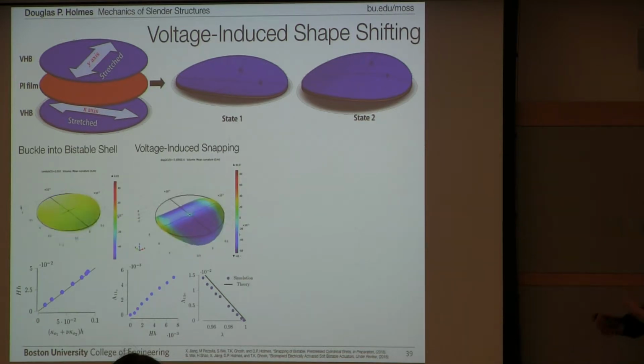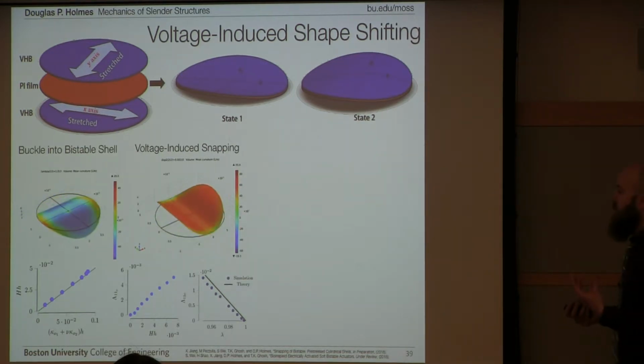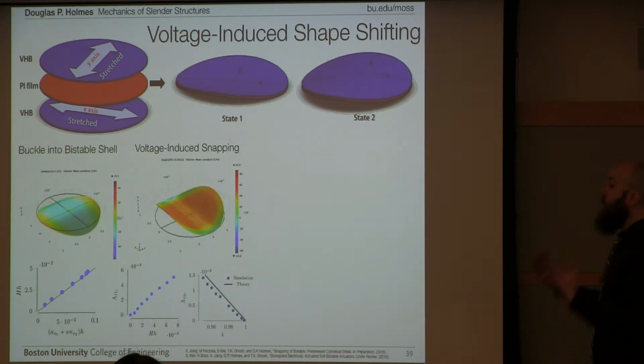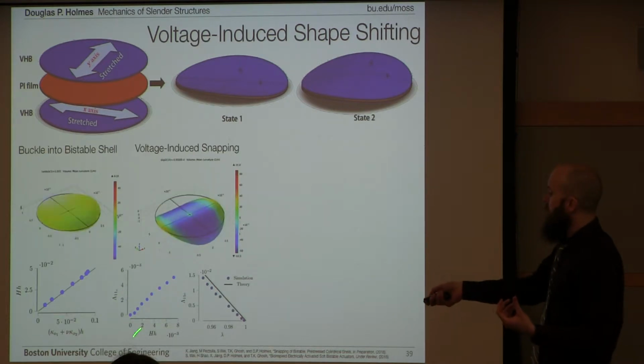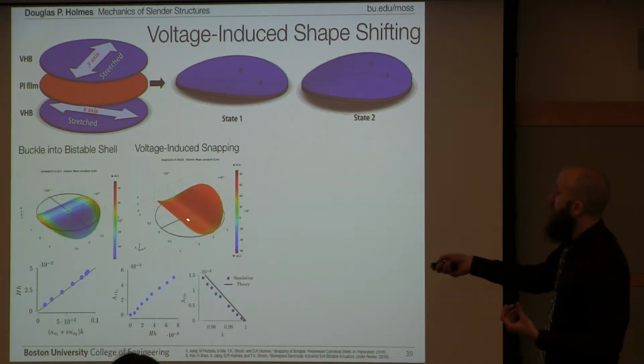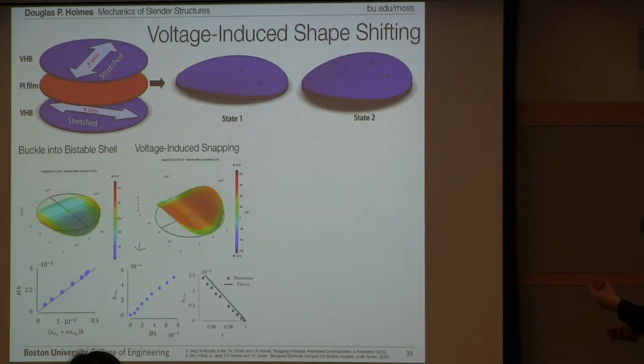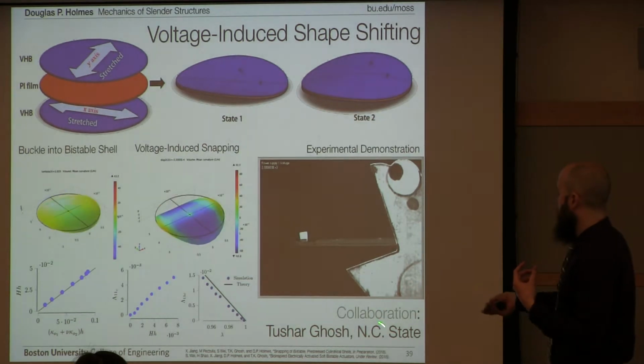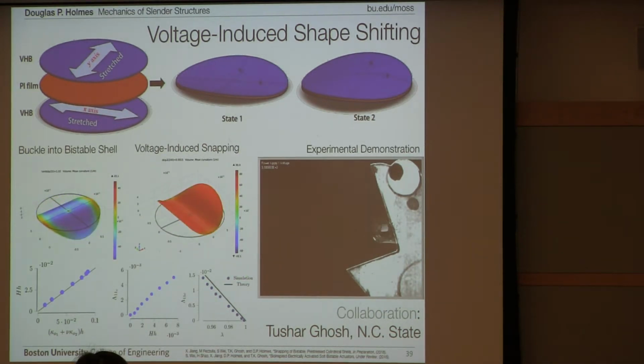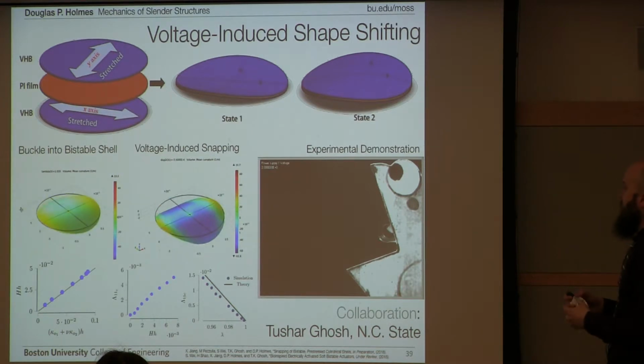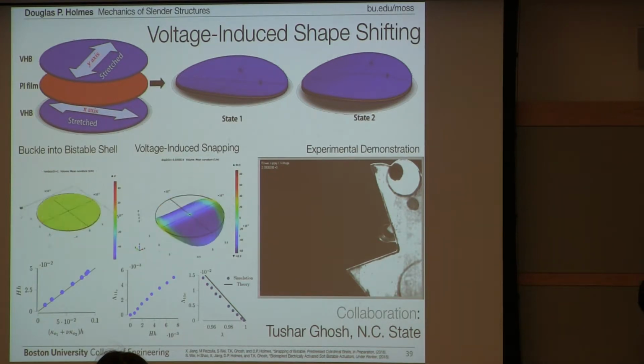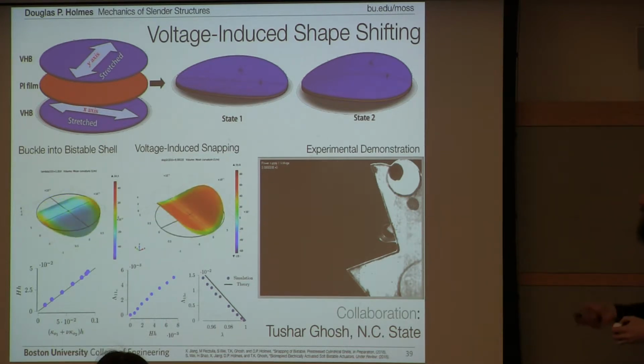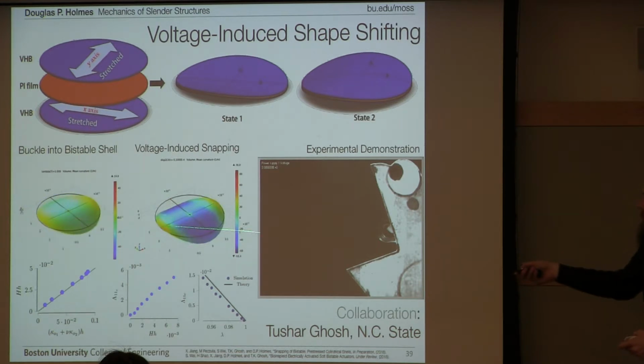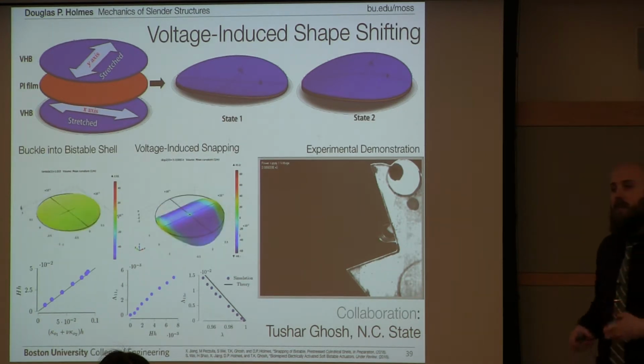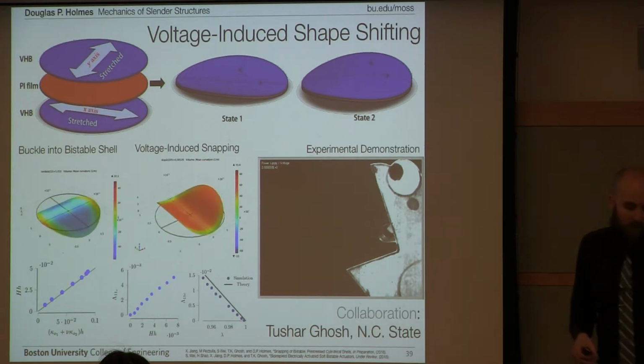And that's important for this reason. If you want to create a bistable shell that can snap between two configurations, the amount of voltage you need to give it to snap depends on how curved it is in the first place. So the amount of voltage here goes up with the amount of curvature your shell has. And so these are simulations that show how this bistable shell will snap as we apply this voltage to it. In collaboration with Tushar Ghosh at NC State, we're now experimentally realizing these bistable structures. This looks like a snap bracelet, because it's exactly what it is. It's the snapping of a cylindrical shell. If you make one axis of that cylindrical shell really long, it becomes a snap bracelet. And so the mechanics of this are completely guided by the buckling that takes place to form this shape and the snapping that triggers this shape, and it does allow us to make bistable electrically active materials.